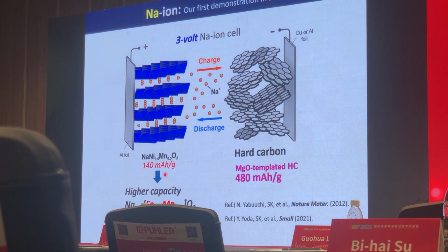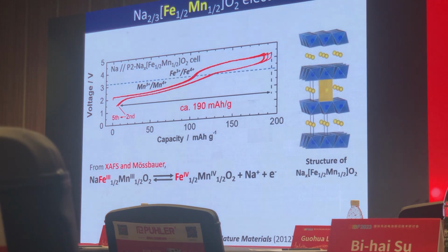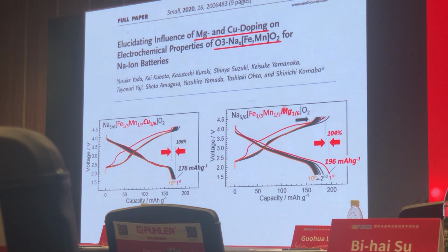First, our trial was based on nickel manganese, and recently a much more abundant positive electrode material based on iron, manganese, and magnesium. So P2 type layered sodium iron manganese oxides are shown here. With the redox reaction based on manganese and iron, the Fe3+/Fe4+ redox couple, we can demonstrate 190 milliamp hours. By doping with copper or magnesium, and also having a larger amount of sodium, we have higher capacity and also higher fast charging capability, which are advantageous to design the A/C ratio of a sodium ion cell.